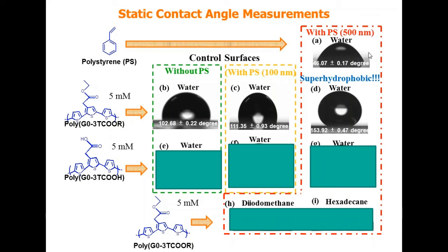This superhydrophobic effect is interesting in that we found properties that are able to resist wetting even at higher temperatures, low pH, or different soil conditions. In fact, it's also resistant to corrosion as well as bacterial growth. And I'll show you maybe some of those results later.